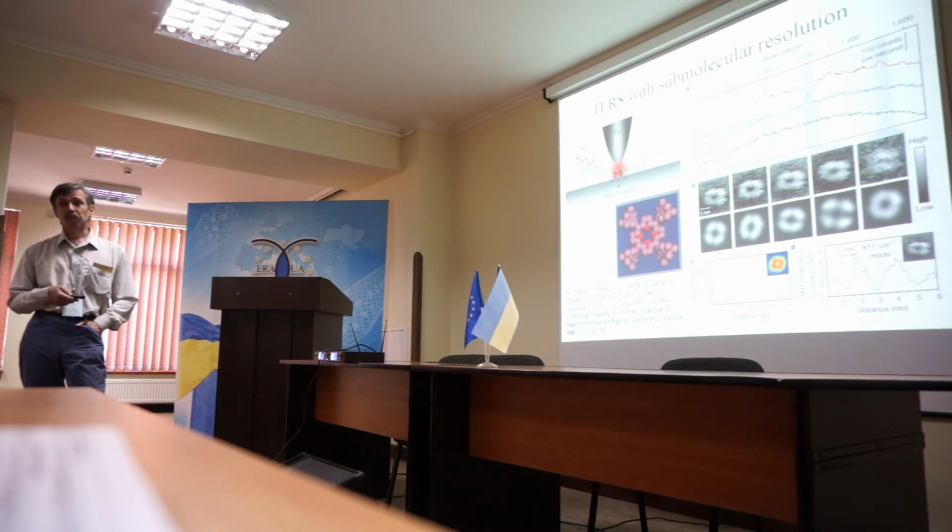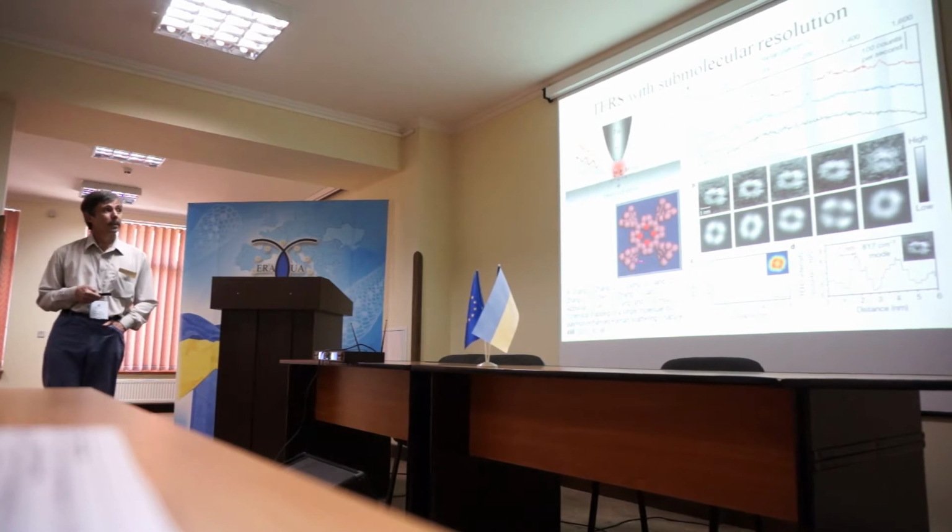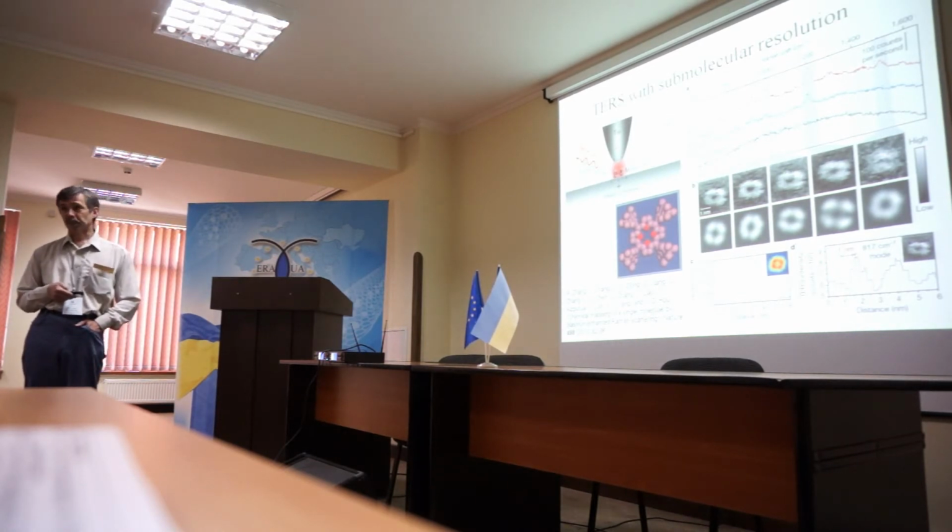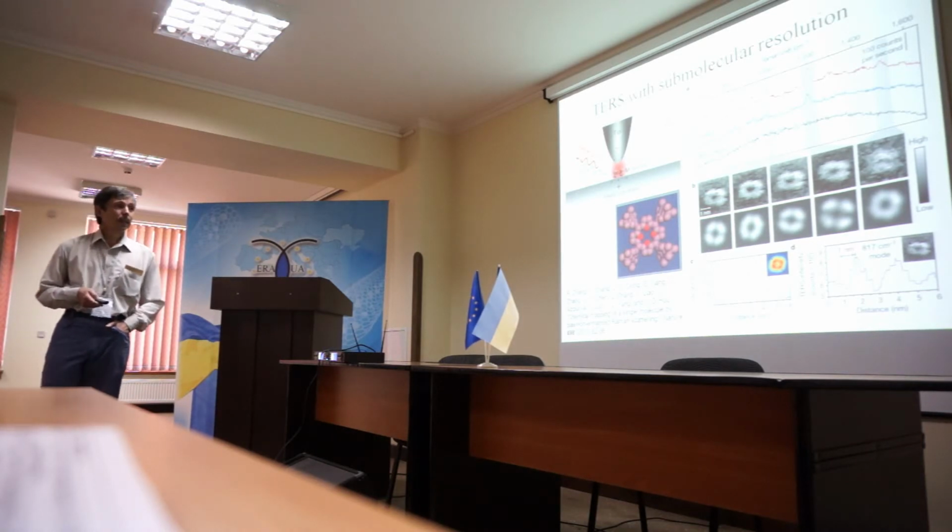And you may see at the moment there are absolutely incredible results. These results were published last summer, where TERS was made with submolecular resolution. Because in addition to the high resolution of near-field optics, here we have non-linear field enhancement, so we have additional field localization. This is a porphyrin molecule with a size of a few nanometers, and you may see the picture of this molecule made with different Raman modes of this molecule. This is the theoretical calculation of this molecule, and this is the experimental one.